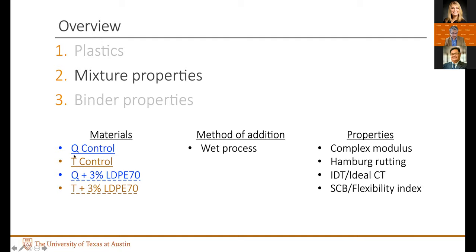The Q and T represent two different binder sources. Actually, they stand for Qatar and Texas because we got one binder from each place. And then we had these controls mixed with LDPE 70, 3% by weight of the binder. We used a wet process. Again, we were looking at the best case scenario here.